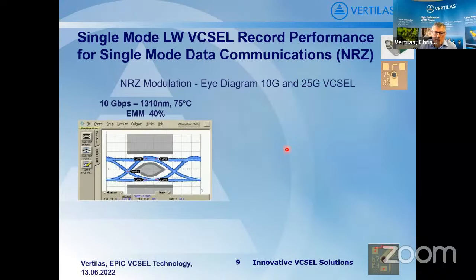So the next slide shows you, for example, a 1310 nanometer laser for 10 gigabit applications. What's really important is that those are uncooled applications, that the lasers not only perform at low temperatures, but also at very high temperatures like 80 or 90 degrees. Here's an eye diagram where you can see a 75-degree eye with a mask margin of 40%